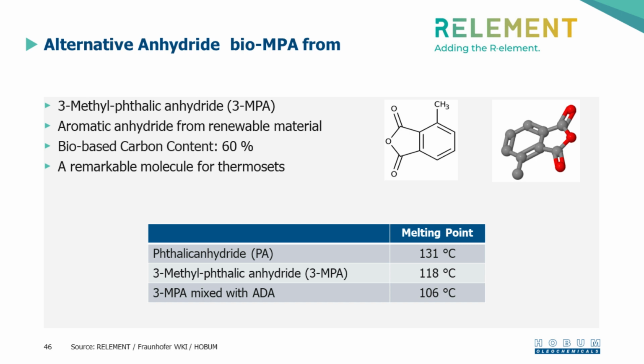Why is it a remarkable molecule? Phthalic anhydride is already used in the industry for many years, has a melting point of 131 degrees. 3-methylphthalic anhydride from renewable resources has a considerably lower melting point of 118. And if you mix the 3 MPA with our ADA, you have a eutectic effect, and you even lower the melting point to 106. So at 106, it's completely molten and liquid.